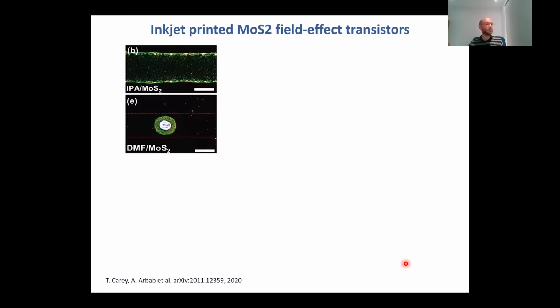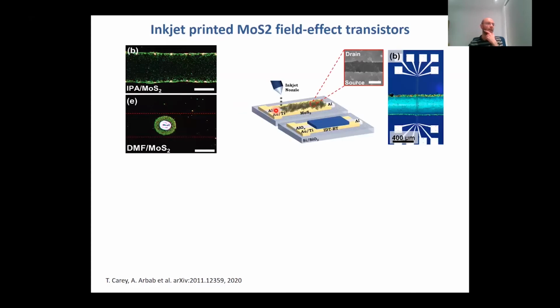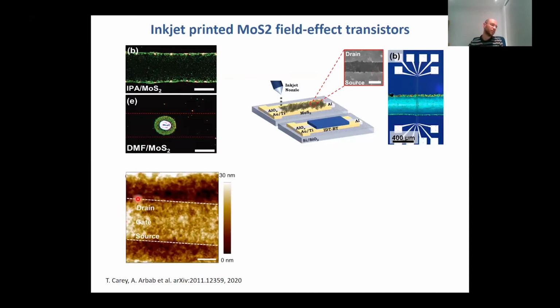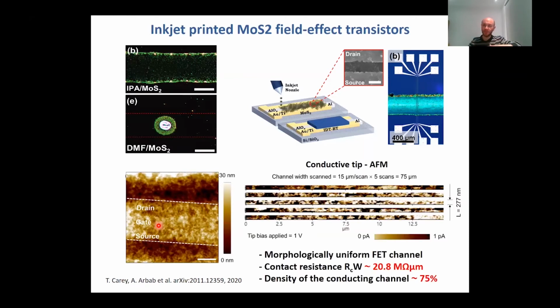Then we worked on improving the printability with, again, the tricks I showed you earlier on, so surface tension and density. And then we try to print devices. In this case, we have fully printed MoS2 FETs. And here we can see the MoS2 flakes bridging source and drain. And then we take a look at the morphology of the gate. We see that it's uniformly covering source, drain, and gate. That's exactly what we want, to have a uniform conductivity between source and drain. And also, thanks to conductive AFM, we can actually check what percentage of this channel is actually conducting. So here we're really looking at the conducting path between source and drain. We work out that around 75% of the channel is conducting.